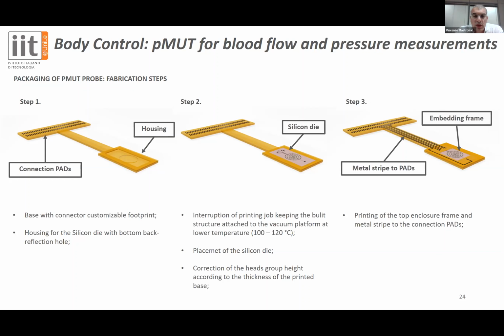Before moving to the printing of the top embedding frame, again we adjust and correct the head group height according to the thickness of the printed base. So we printed the embedding frame that includes the metal stripes that directly connect the pads on the silicon die to the connection pads, and the embedding frame that encapsulates the silicon die, achieving very robust final devices.